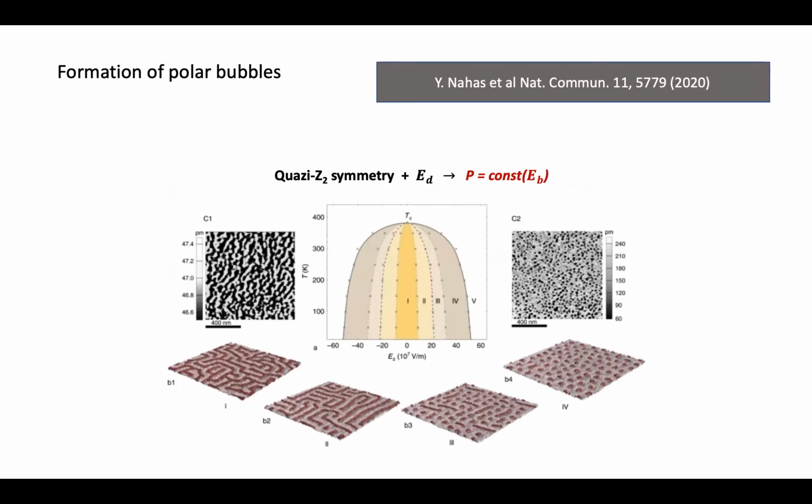Yusra had this idea that because of the quasi-two-dimensional local symmetry, because of the compressive strain, the dipoles are constrained to be out of plane, hence the nanostripe patterns. And because of this strong depolarizing field that governs the width of the domains and fixes it to a certain wavelength, we should fall in the scenario of the so-called constrained order parameter thermodynamics, which actually turned out to be true.